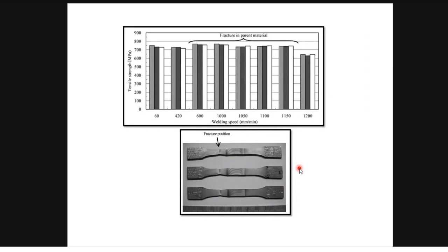But the failure doesn't occur in the weld region. It's away from the weld region. That's in the heat affected zone, where the temperature is exposed to 600 to 700 degrees centigrade.